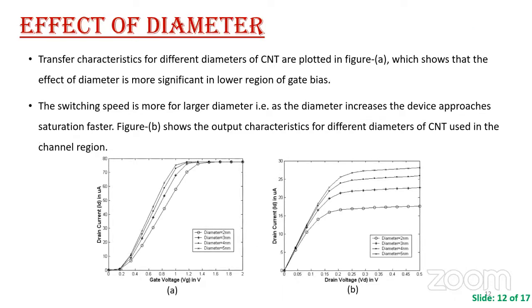Effect of diameter. The transfer characteristics for different diameters of CNT are plotted in figure 1, which shows that the effect of diameter is more significant in the lower region of gate bias. The other one shows the output characteristics for different diameters of CNT used in the channel region. From the figure, it is clear that the drain current is more for higher values of diameter, and the difference increases as we go to higher values of diameter.